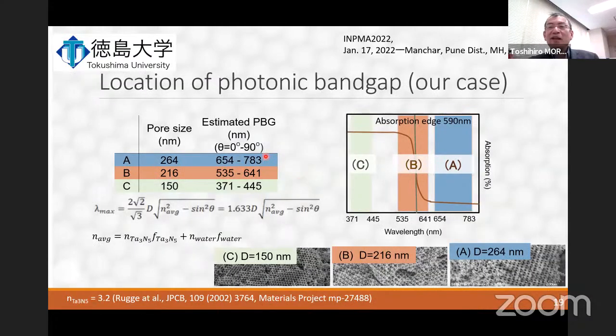But we estimate the location of the actual photonic band gap in the absorption spectrum of our samples. In the visible region, the absorption edge exists as well as the photonic band gap in the three samples like this. Unfortunately, we are not able to determine the photonic band gap for each sample directly because of their opaqueness. They are not transparent, so at that moment we cannot determine the exact photonic band gap position. So we calculate the photonic band gap by the Bragg equation using the pore size. We adopt the refractive index of tantalum nitride, usually reported as 3.2, and assume that the photonic crystal powders were made of ideal inverse opal structure.